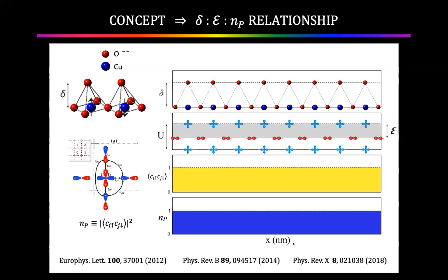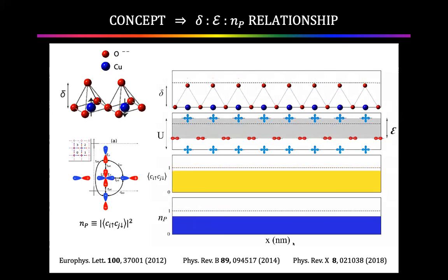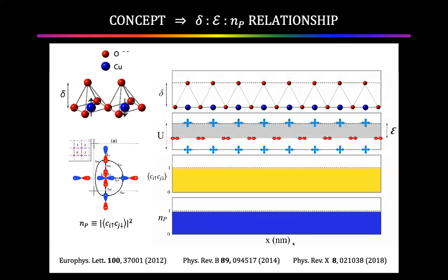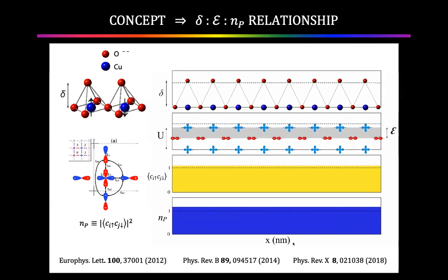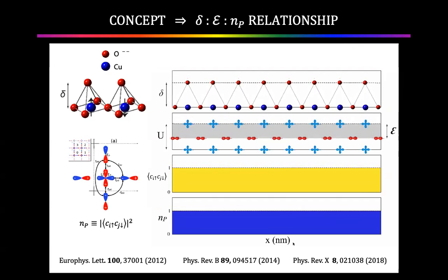So the concept we started with is we want to move the apical oxygen atom. We want to find out what does it do to the electronic structure here, specifically what does it do to the charge transfer energy as it moves around. And then what does that do to the superconductivity? So Wang Ping Ren made this nice movie to schematize his ideas. You want to move around. So if you move down, the charge transfer energy goes up. If you move up, the charge transfer energy goes down. When the charge transfer energy goes up, the superfluid goes down. When the charge transfer energy goes down, the superfluid goes up. All in the linear approximation of small changes. Even the sign of this is interesting, right? But the proposal is that as you move the apical oxygen away, you get more superconductivity, which is something that material science people have believed for a long time in these compounds.